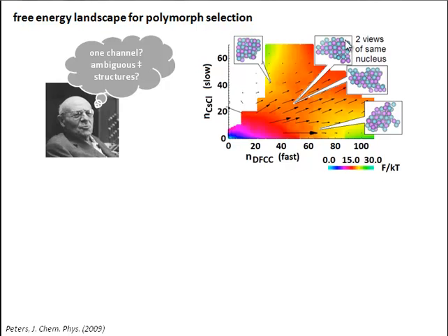structured, right? So from one direction, I see a nucleus that looks like it's approximately cesium chloride ordered. And if I just rotate that nucleus around, I see a new vantage point where it looks like it could be an FCC nucleus, okay, with a hexagonal packing. Now the truth is that it's sort of imperfect on both structures. And it can tolerate that imperfection because it's still very small.